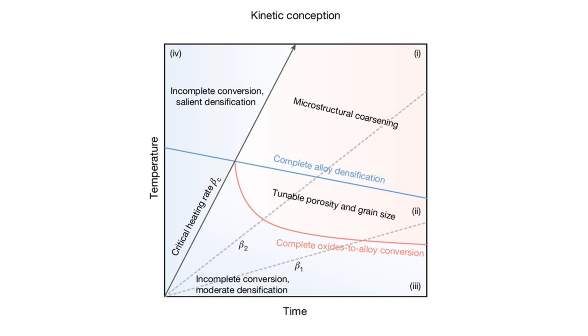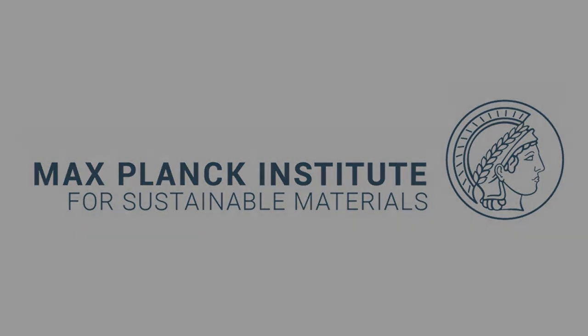As you can see on this slide, this allows us to produce metals already the size of a coin in the laboratory, which come out as ready-to-go compact bulk alloys. We also discover many new features during this process: rather than a linear sequence of reduction of individual oxides, there is complex co-partitioning between the oxides and the metals. Thank you very much for your attention, and I hope you read the full paper.